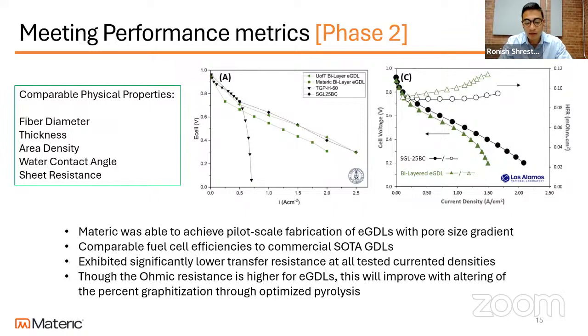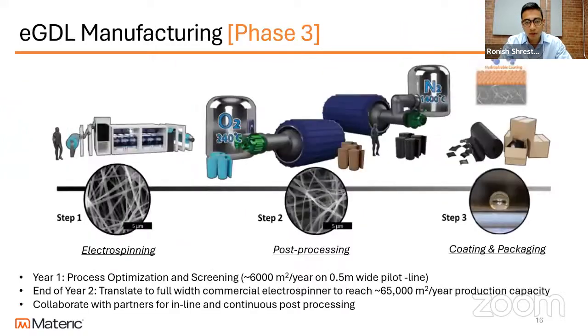And then finally, as part of our 4-year collaborative effort, we'll be scaling up this process. Year 1 will still be optimizing and screening in the pilot line itself, but we'll still be producing around 6,000 square meters on a 0.5 meter wide pilot line. At the end of year 2, we'll be translating the electrospinning process to a full width, about 1.6 meter wide commercial electrospinner to reach that production capacity of 65,000 square meters per year.